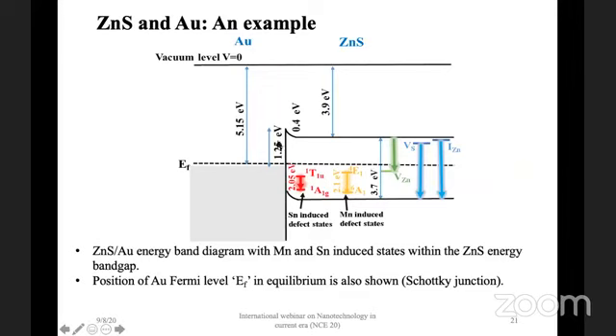On the left side, we have gold. So this is the Fermi energy of the gold, which is in thermal equilibrium with zinc sulfide. And we have the defect states given over here due to zinc vacancies, sulfur vacancies, interstitials, and due to manganese and tin defect states. This is the barrier height. We have around 1.25 eV. We have the conduction band over there in the case of zinc sulfide. So the right side is zinc sulfide, the left side is gold.